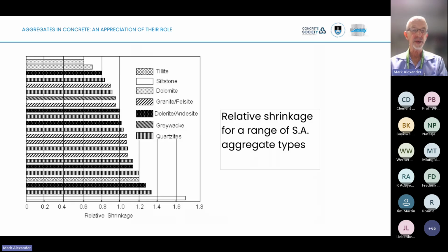And then if we look at the restraint effect, here is one over here. So for example, there are the dolomites. This is relative shrinkage for a range of South African aggregate types. We've got all of them here in that legend. And up at the top, there's the dolomites. They are very low shrinking materials, in concrete that is. And down at the bottom, we've got a siltstone, which is a high shrinking material. And you can see exactly what it does to concrete shrinkage. And here again, the shrinkage could differ by a factor of 2, depending on the aggregate type.